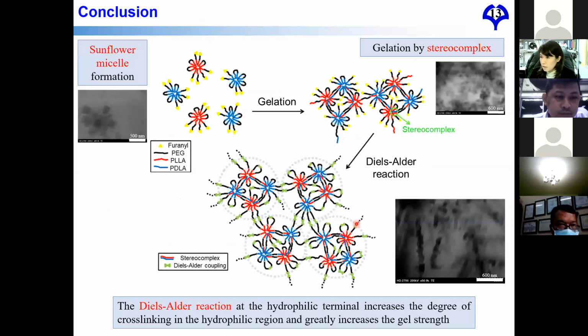So this is the conclusion about this work. As you can see here is a TEM result. First we mix the diblock copolymer and triblock copolymers, and then make sunflower type micelles. So you can see that it's the sunflower type micelle.